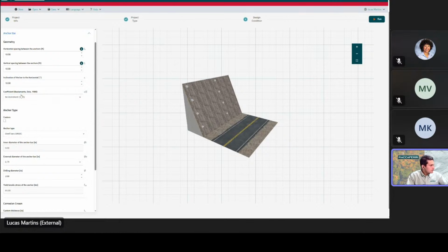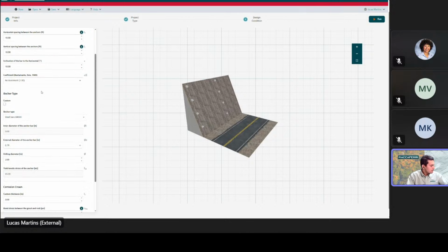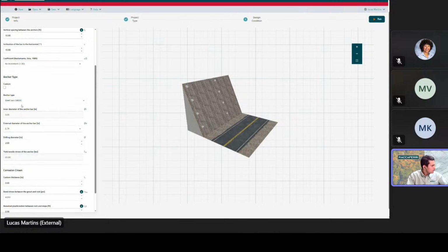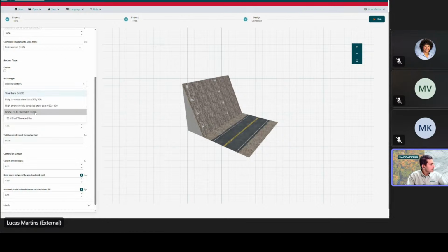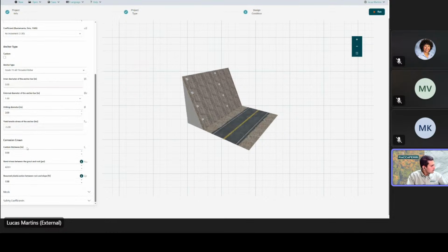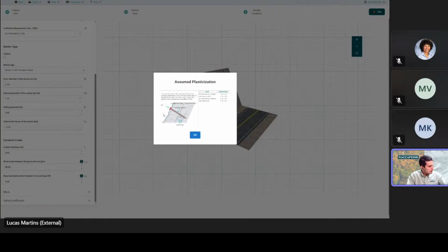You can enter coefficients to increase the anchor drilling diameter, or leave it at 1 for no increment. For the anchor type, we usually use threaded bar. It can be hollow bar or steel bar. If you want to use a hollow bar, you can enter it as custom. But let's go ahead and enter a grade 75, number 8 bar with a drilling diameter of 3 inches. Corrosion thickness and bond strength are the same parameters we saw in the simple drapery. This will calculate the anchor embedment. The plasticization is the shear band length. You can have values here too.